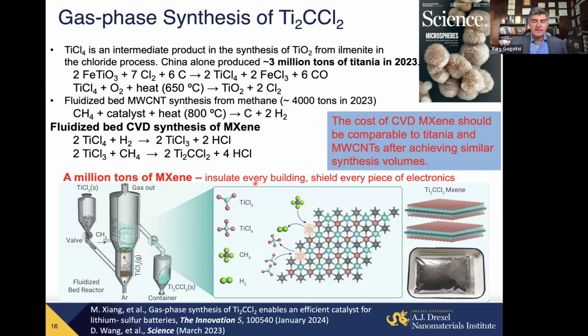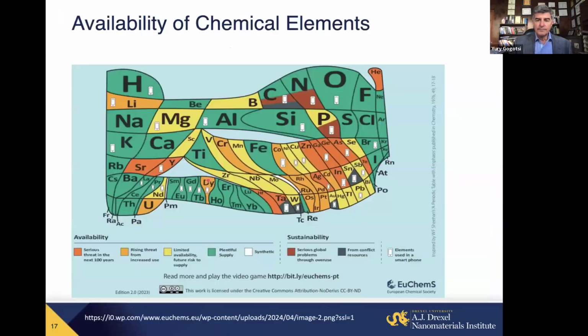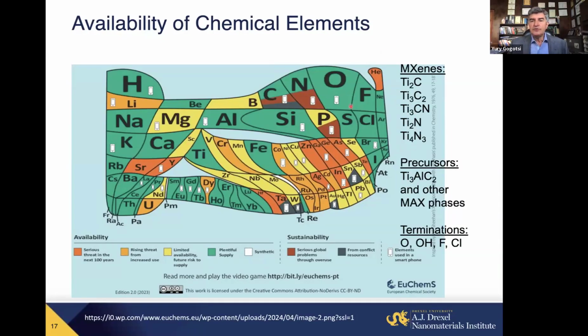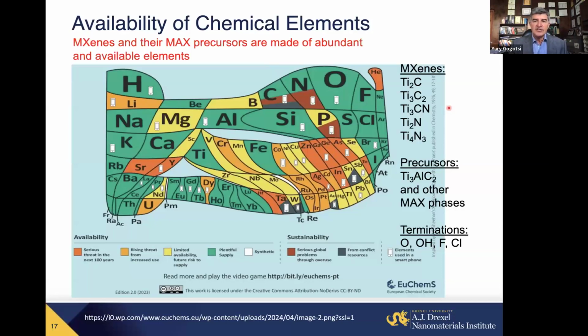Say, insulate every building, so that there will be much better temperature control, minimize the need for air conditioning or heating in winter. There is something else very important. There are some wonderful materials, tellurides, gold, platinum, which are made of rare and expensive elements. However, the majority of MXenes being studied contain titanium, carbon, nitrogen. We etch away the aluminum or silicon layer. We have on the surface fluorine, oxygen, hydroxyl, chlorine. So all very abundant elements. And if you use abundant elements, it means it's only economy of scale, making large amounts of materials, and you can make them at low cost and again in large quantities. So again, it's a real technology.